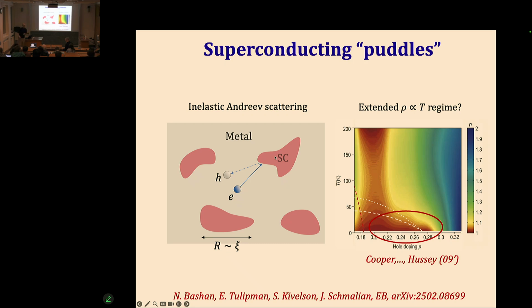What we assumed is that we're far enough away from the superconductor to metal transition such that these couplings are weak. These puddles are far enough apart compared to the thermal length or the magnetic length that their coupling is very small compared to the typical charging energy. In that regard, the Josephson coupling between the puddles would be a subleading effect. It would contribute something to the conductivity, but we assume that the conductivity is actually dominated by the normal electrons, not by Cooper pairs. That is what you assume, that's not necessarily how it is, right? No, absolutely. This is the assumption of this entire analysis. It would only work if we're far enough from the metal to superconductor transition, where these Josephson couplings for sure are going to become important.